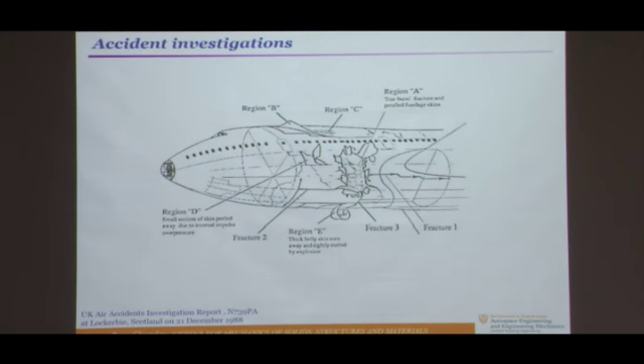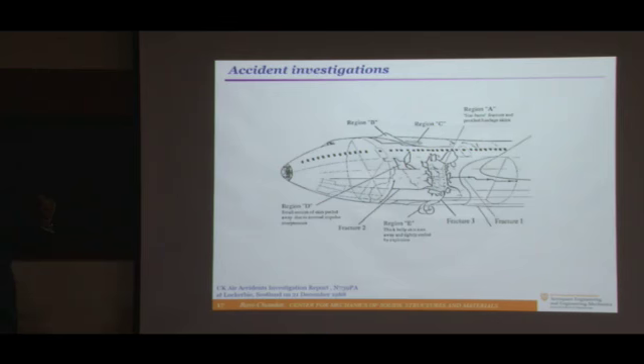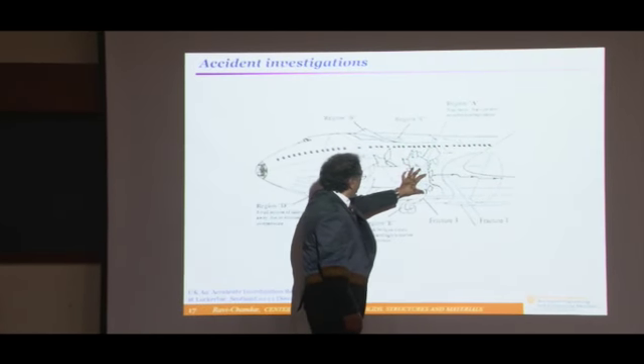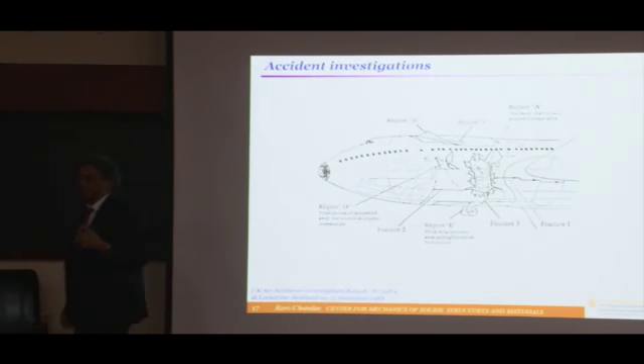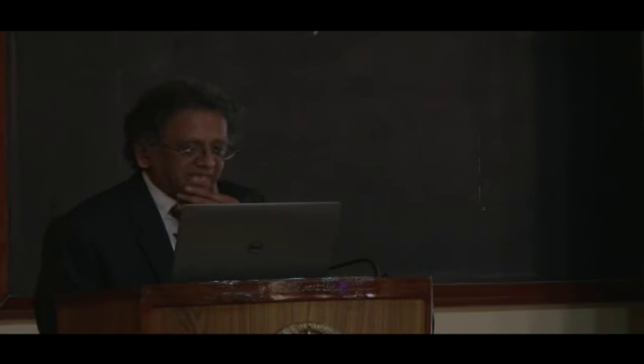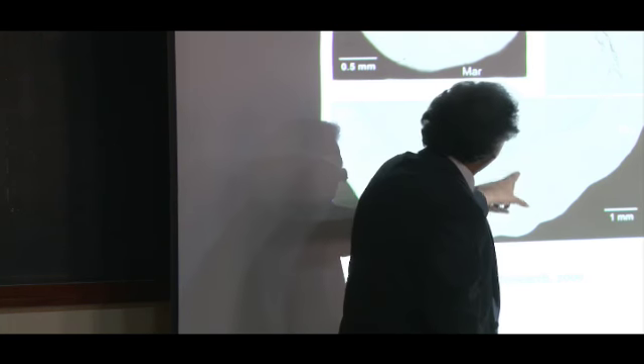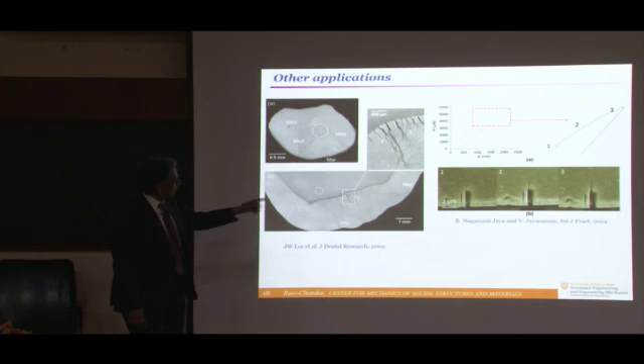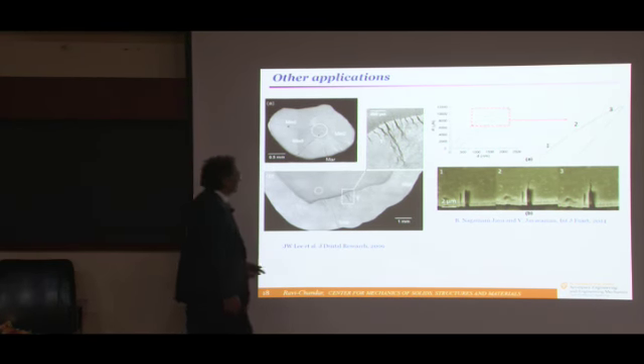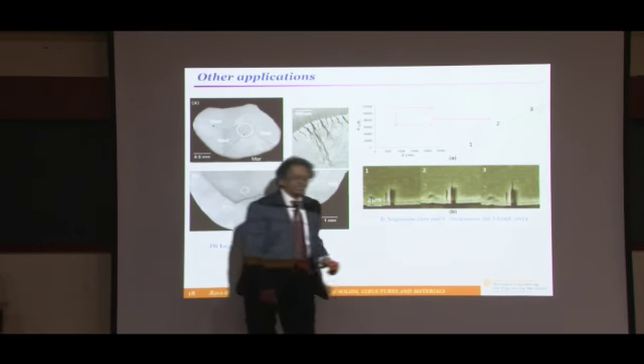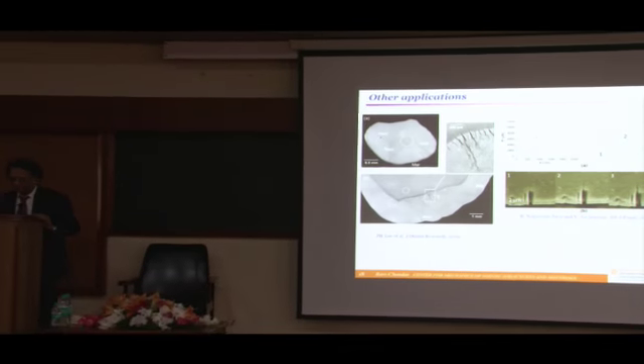And they fall into one or more of these categories. In order to design against them, all you need to do is calculate the energy that can be released by the elastic system and whether that's sufficient to feed the fracture energy that's needed in order to create that new fracture surface. Much of this framework was developed by Griffith in about 1920 and then finished in about 1924, but it wasn't used because it was very difficult to implement in practice. In other words, it was difficult to calculate this for arbitrary crack geometries. So it took another 30 to 50 years to fully formalize this theory of fracture. And it took the role of two additional individuals, George Irwin and Max Williams, to bring about the right criteria for practical use.